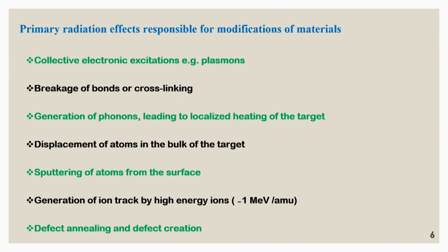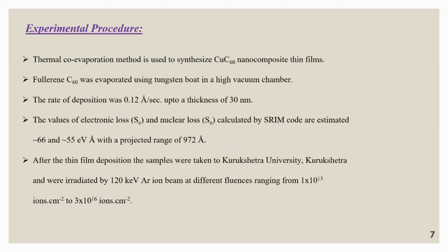Primary radiation effects responsible for modification of materials are collective electronic excitations, which are known as plasmons, breakage of bonds or cross-linking, generation of phonons leading to localized heating of the target, displacement of atoms in the bulk of the target, sputtering of atoms from the surface, generation of ion tracks by high energy ions, and defect annealing and defect creation.